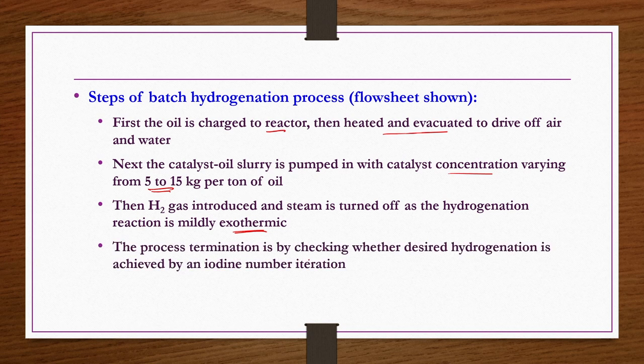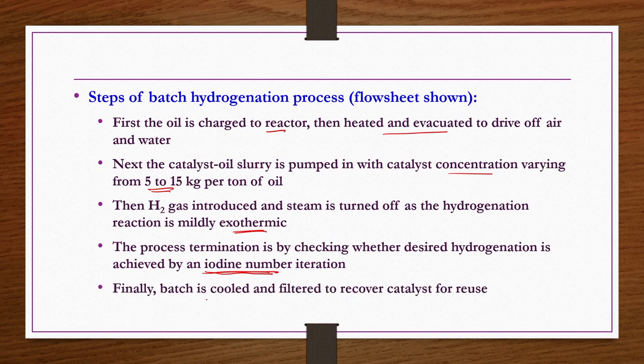The process termination has to be checked. How do you check? You continuously keep measuring the iodine number, right? If it is as per the requirement of the oil, then you should stop the hydrogenation process, and then start the subsequent deodorization. Finally, the batch is cooled and filtered to recover catalyst for reuse.